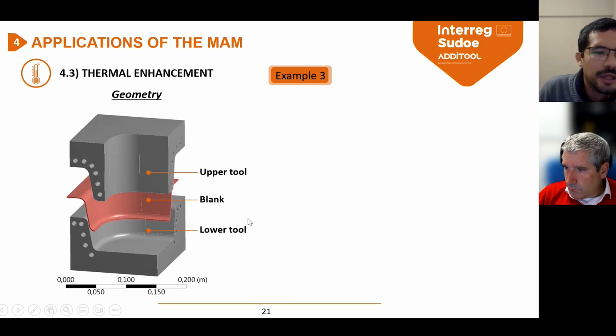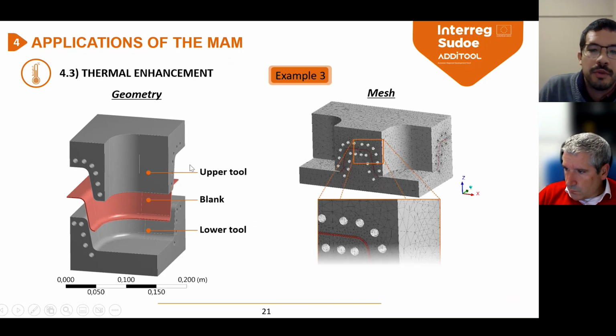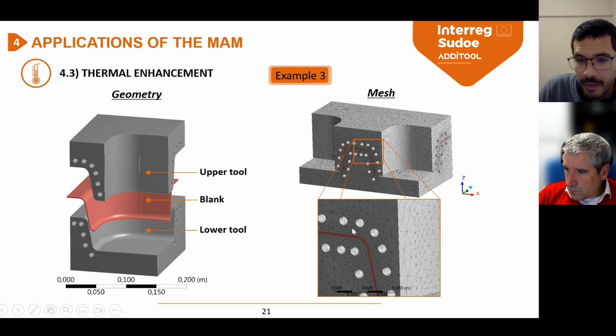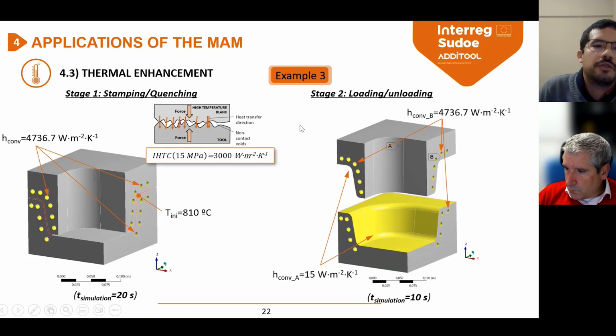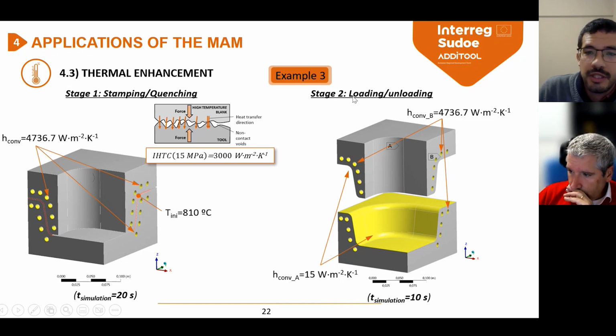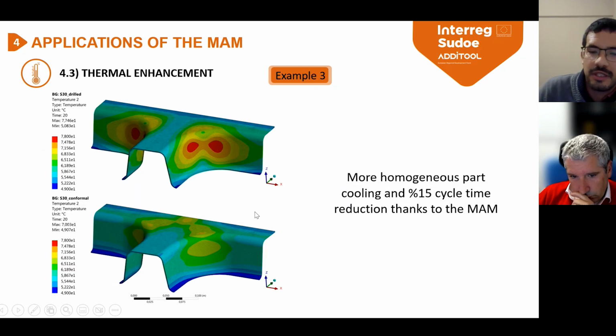For this purpose, we designed the upper and lower tools, also the blank geometry. We performed the meshing in order to refine the element size in the area close to the contact regions and the cooling channels. We introduced the boundary conditions, and here we can differentiate two operations. First of all, the stamping and quenching operation, in which we have a hot blank in contact with the tools and we are extracting heat through convection. And the second stage is the one corresponding to the loading and unloading operation of the blanks. In order to obtain a stable regime, we perform 30 consecutive stamping operations.